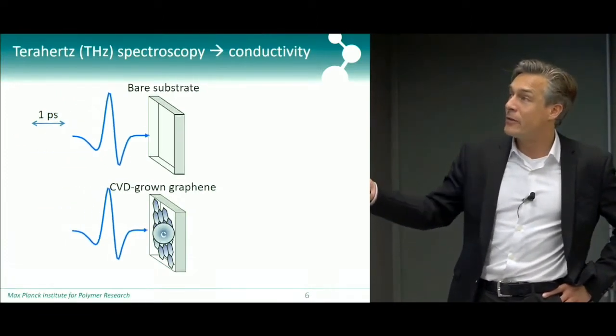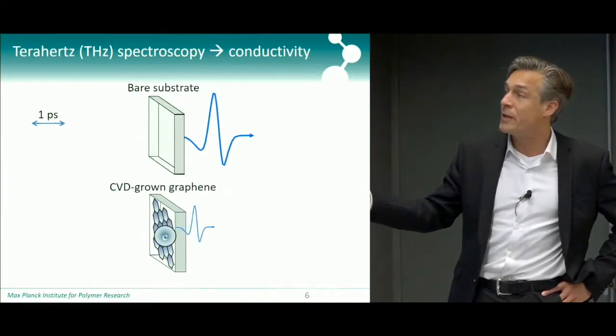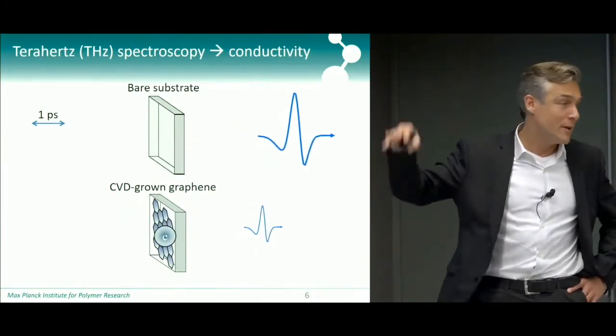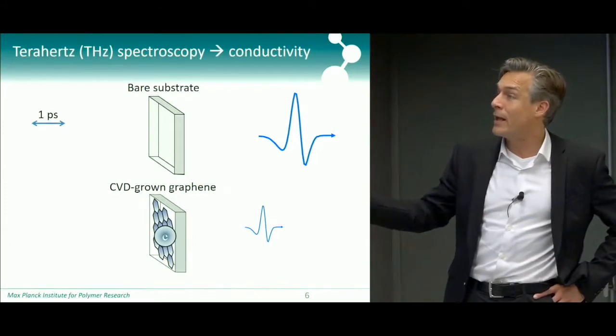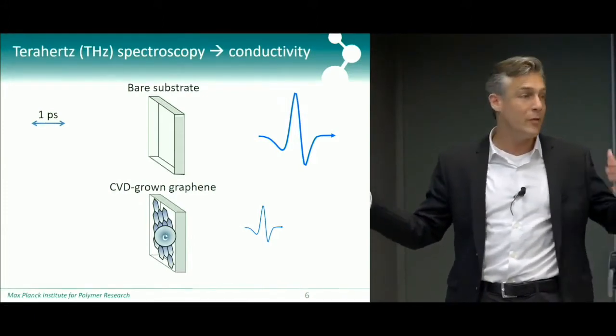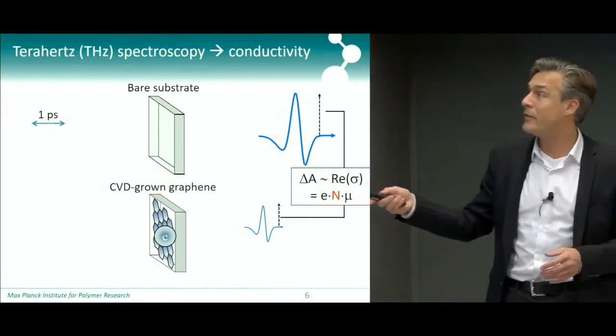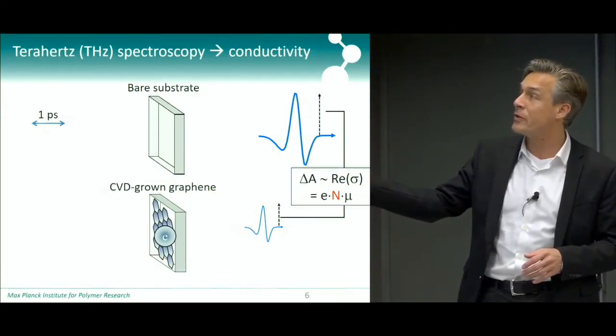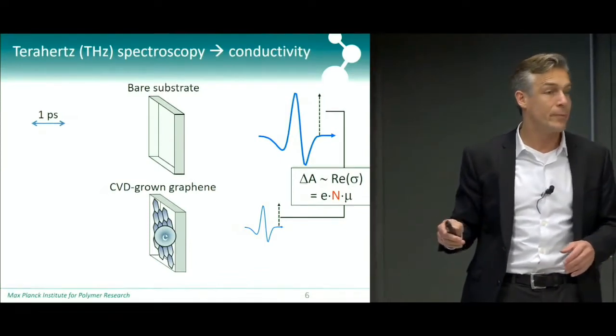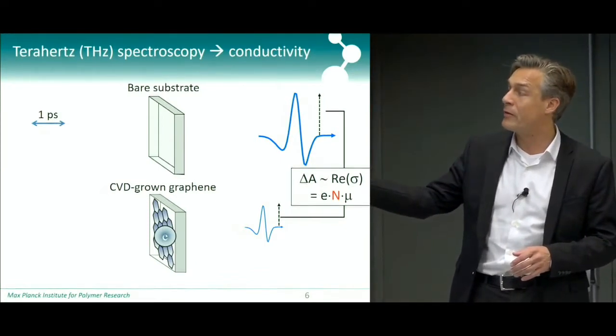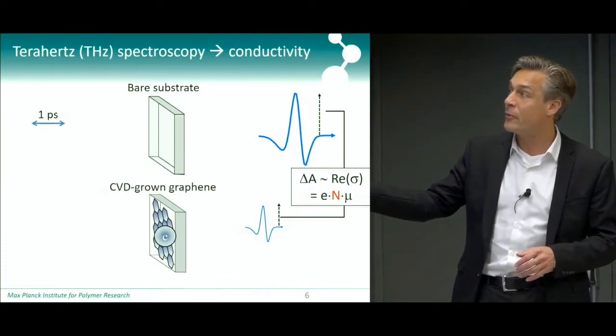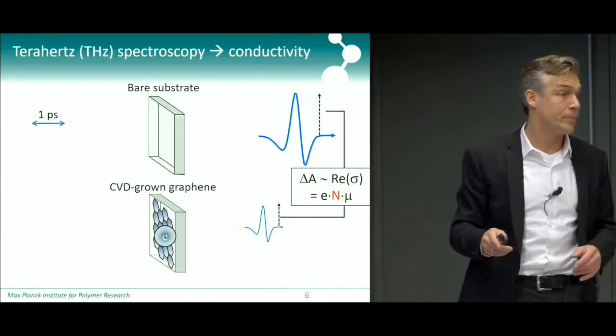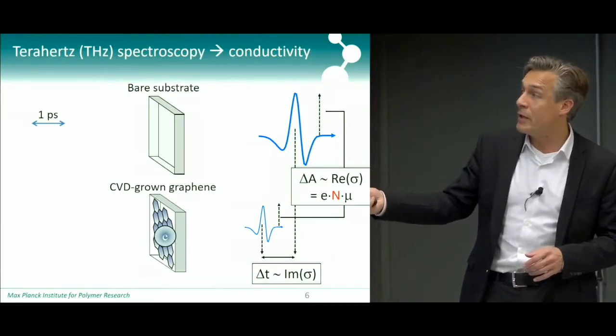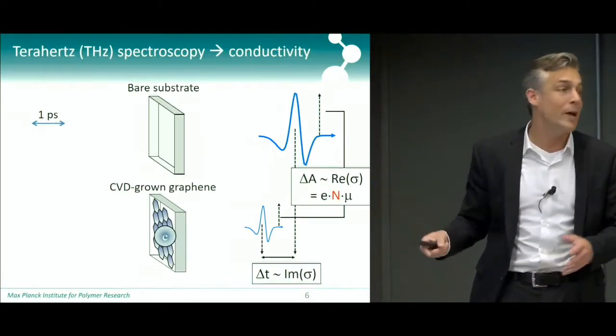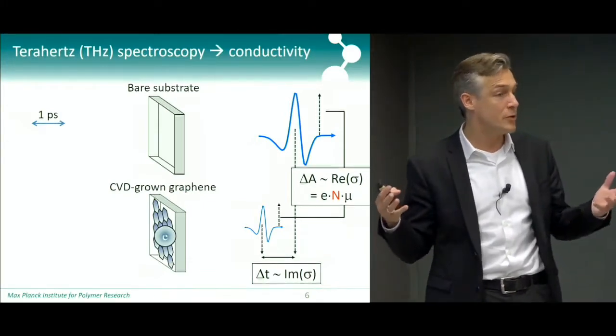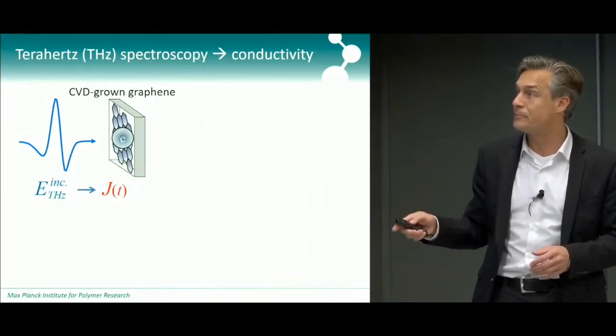And so when we do that, the one pulse doesn't do anything. The other pulse accelerates the electrons in the material, and that causes a reduction in the amplitude and a phase shift of the pulse. And that reduction in the amplitude is a direct measure of the real conductivity of the material. And that real conductivity, again, is a product of the number of carriers that we have in there and their mobility. And the phase shift that you see is a measure of the imaginary conductivity, or the polarizability that is induced by the presence of these free electrons.